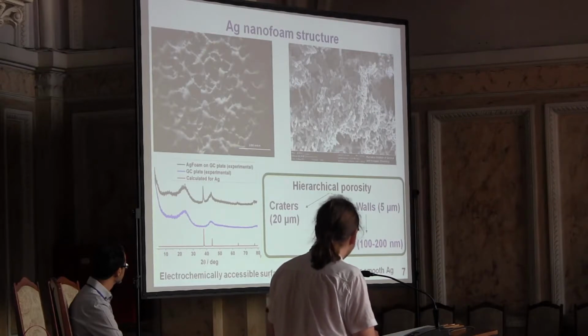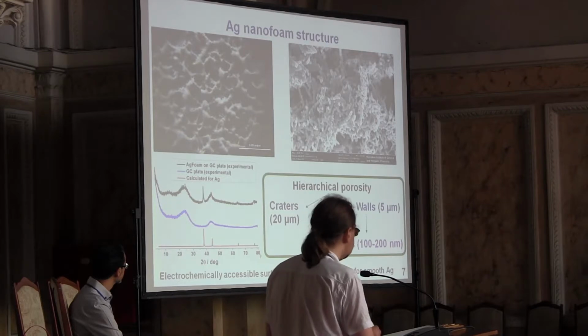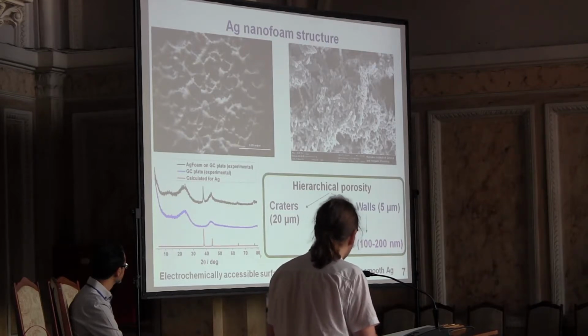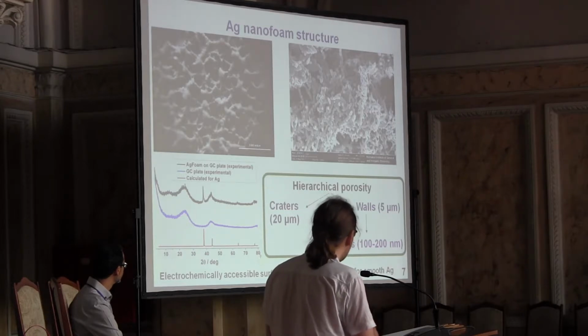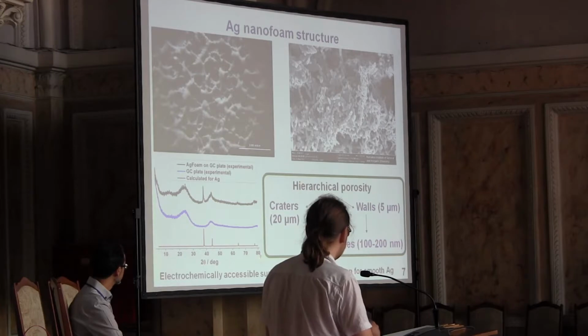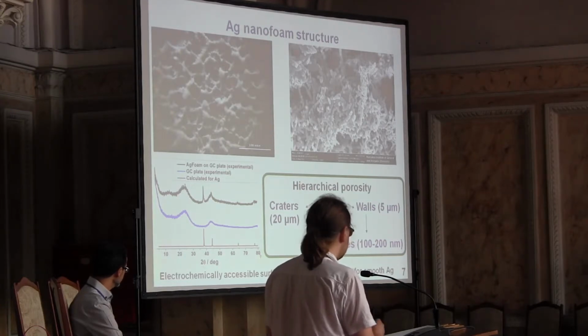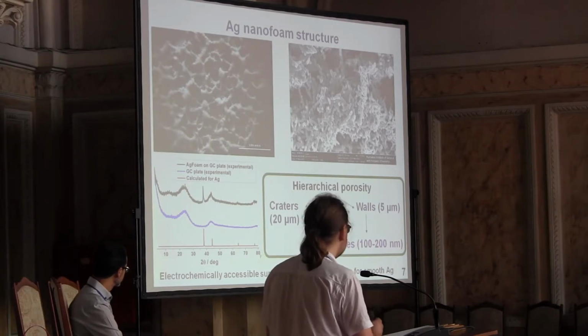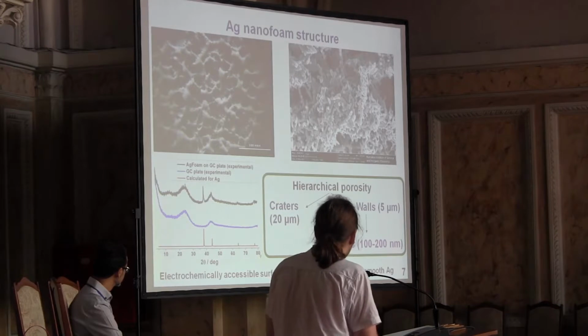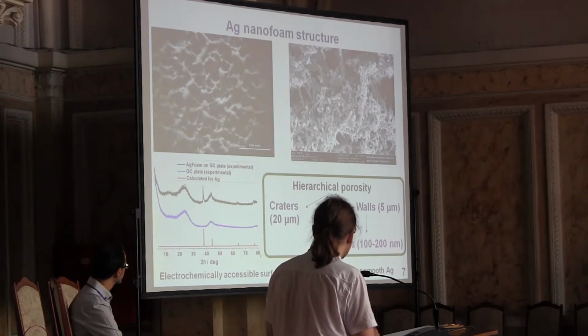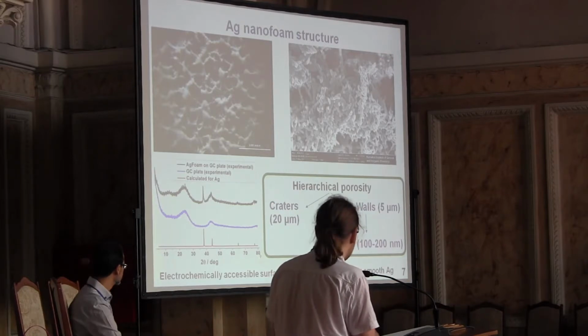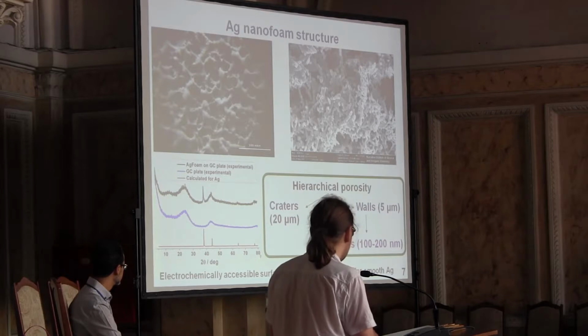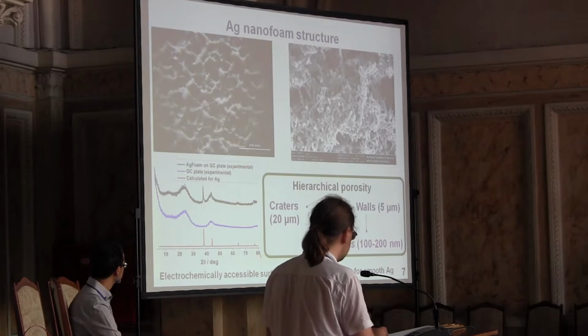It was shown that the resulting nanofoam possesses hierarchical porosity with two levels. First level consists of craters separated by walls. And the second level is presented by a dendritic nanocrystalline structure of the walls. Presence of crystalline silver was confirmed in the samples, and it was shown that electrochemically accessible surface area of this coating was approximately 8 times higher than for smooth silver cathode of the same square.